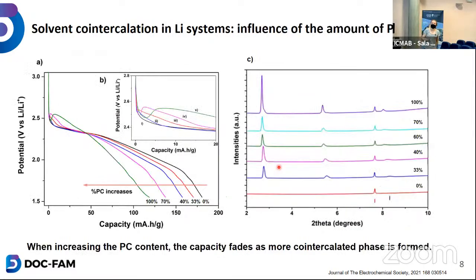However, if you fix the salt and you increase the quantity of PC in your electrolyte, your capacity is fading. And you also have some nice electrochemical signature of the nucleation of the phase at the early stage of reduction. If you look at the X-ray diffraction pattern, you will see that the more you increase the quantity of propylene carbonate, the more intense the co-intercalated phase is. Which means that as long as you can co-intercalate, you will co-intercalate solvents.